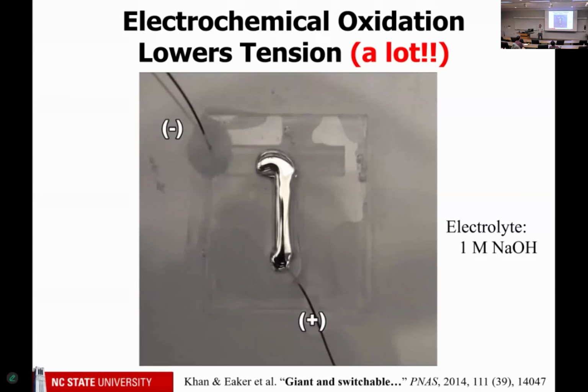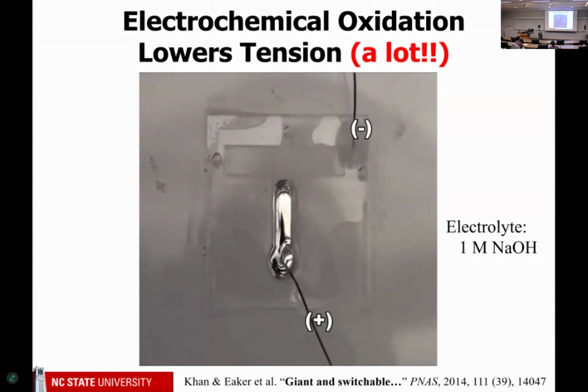Remember, surface tension is 10 times that of water, which means it really wants to be a ball. Now you can see at the counter electrode, there's little bubbles forming. That's hydrogen that's being formed. So we're reducing water while we're oxidizing the liquid metal. Okay, so this is really weird, and you should be asking yourself why.